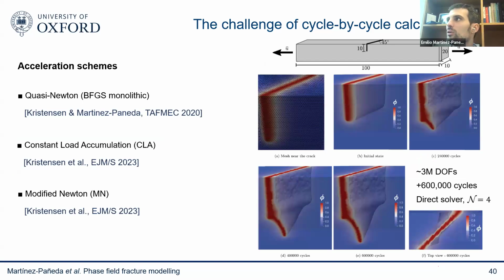This is an example from some years ago. You can see here, this is a 3D component where it has a notch or a crack that has a funny shape, it's tilted, which will lead to some sort of mixed mode cracking. You can see that the cracking is unconventional. And because the cracking is unconventional and we want to capture it, we have a very fine mesh with 3 million degrees of freedom all around the potential area of growth of the crack. And we're solving, you see here, 600,000 cycles. Now we can do millions. And this is, by the way, using a direct solver and doing 1 every 4 cycles. So we could be much more aggressive in the cycle jump scheme.